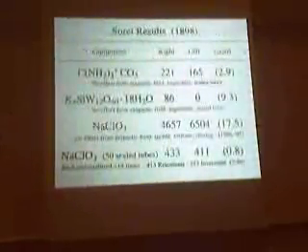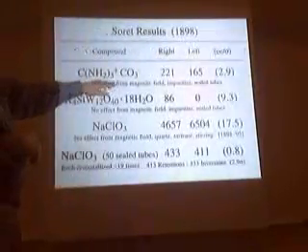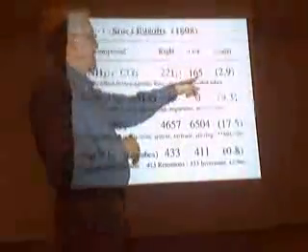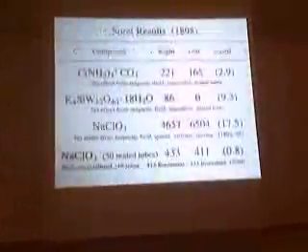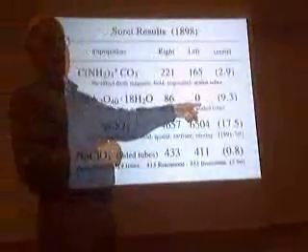Okay, but anyhow, in 1898, he was working on this subject, which was a very popular subject at the time. So he did this carbonate, and he found 221 right-handed, 165 left. That's 2.9 sigma. He didn't use sigmas, but you can see that it's quite significant. Or potassium silicotungstate, 86 to 0, right? He said there was no effect from magnetic field or from impurities.